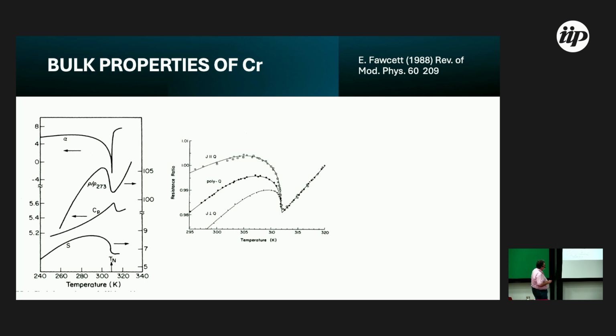In these measurements, this reference is important. The poly-Q state is not a prepared state of chromium. In the single Q state, with the current parallel to Q or perpendicular to Q, you cool down the sample in a high magnetic field.